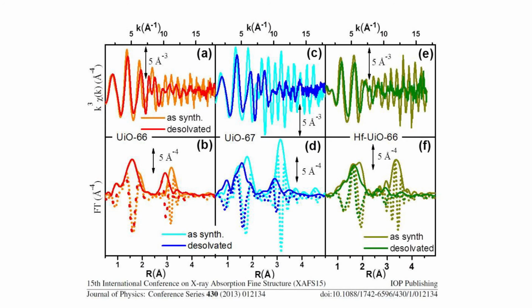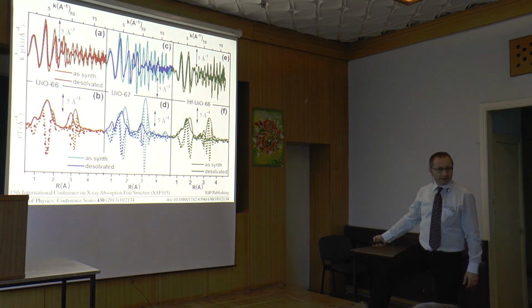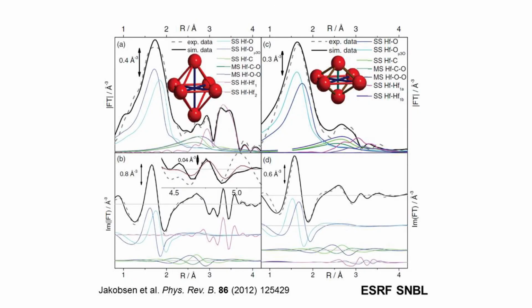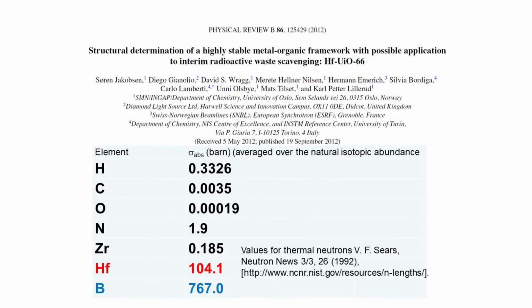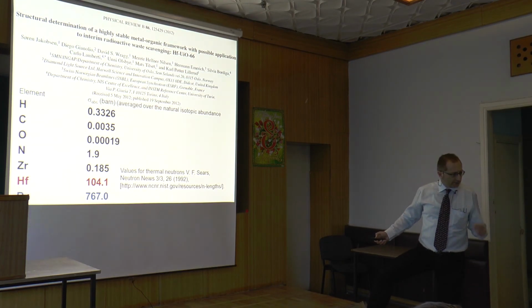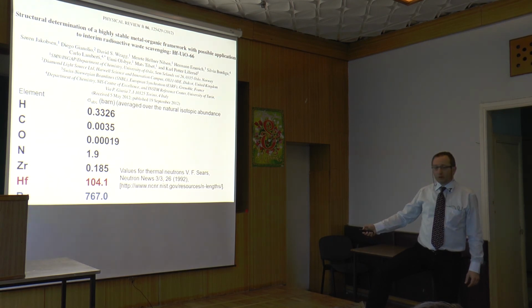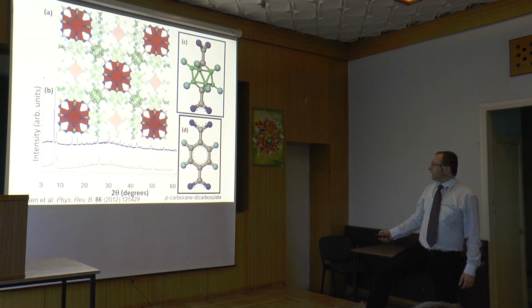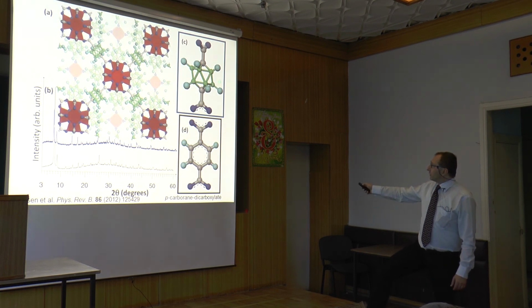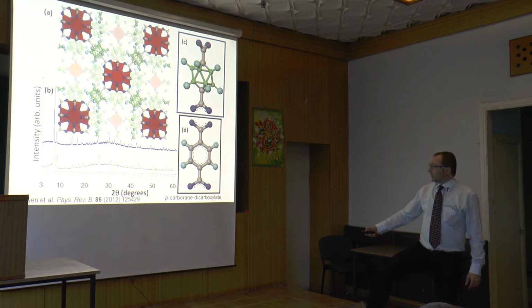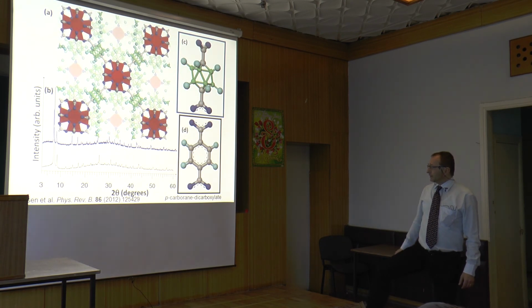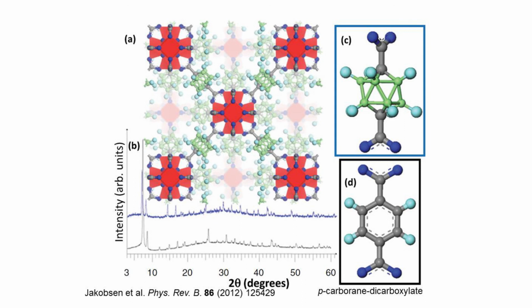And again, the EXAFS, so you are familiar with this too, we discussed it before, and with the hafnium it is exactly the same story. This is more detailed on the EXAFS data analysis, but this is not finished because our fantasy is not limited, and if we could make a linker having boron inside the linker, then this ability to stop neutrons will be even more important. This has been done, so we changed from this standard ligand into this ligand that has boron atoms in the green one. This is the X-ray pattern. It's not perfect, but it is there, and this will be really impressive for stopping neutrons.